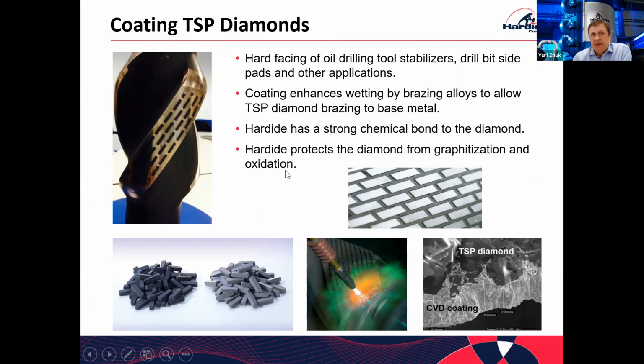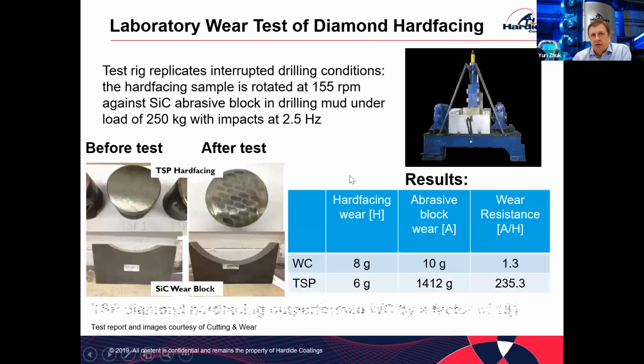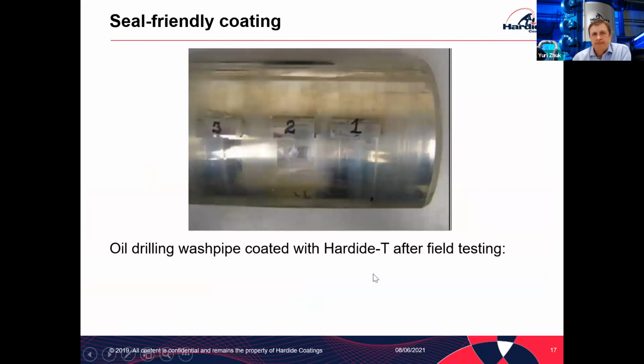We also coat TSP diamonds, which are used in hard facing. The coating enables brazing of that TSP diamond with much stronger retention because the coating has a chemical bond to diamond. Testing of the TSP diamond showed that they can outperform tungsten carbide hard facing by a factor of 181 in wear resistance.